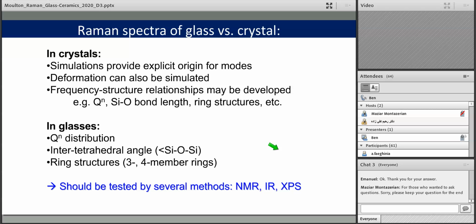So just to summarize what types of vibrational modes we've seen so far, for crystals, it's much easier to make simulations and to get a discrete assignment for the mode and where it originates from. And this allows us to have a much higher sensitivity, not just because we might know where the mode comes from, but because it is much finer and therefore changes to its frequency can be controlled under stress, for example, or other deformations.